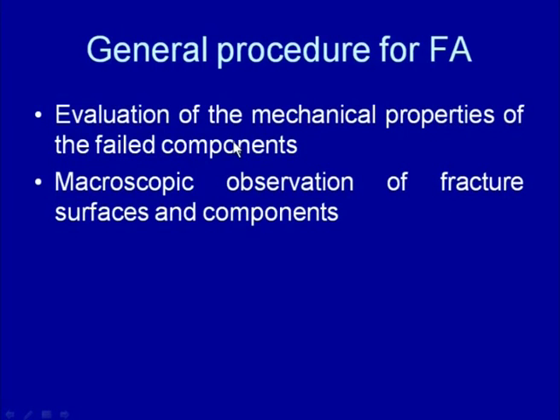but sometimes it is found very difficult to have a big sample from the locations close to the fracture surface. That is why we are not in a position many times to conduct the tensile test, fatigue test or creep test on samples taken from the location close to the fracture surface, and most of the time we rely on the hardness test. So it is common to take a small piece of the sample from the location close to the fracture surface on which a hardness test can be conducted, and from the hardness test we try to estimate the tensile properties and yield strength of the material,